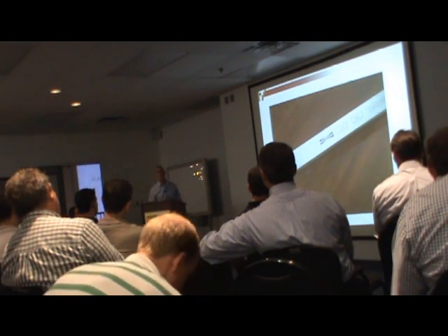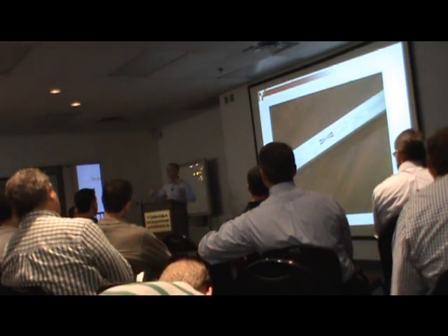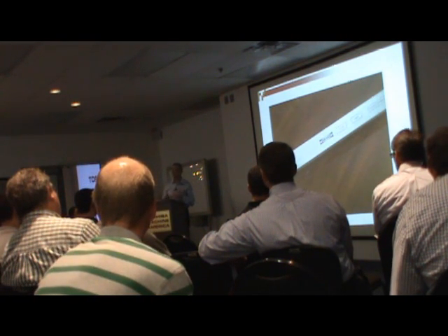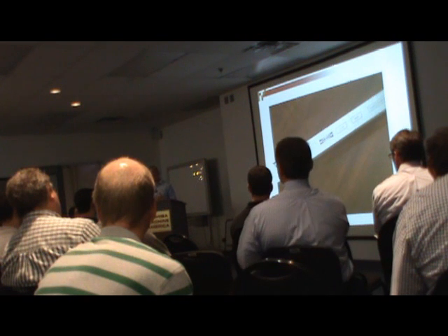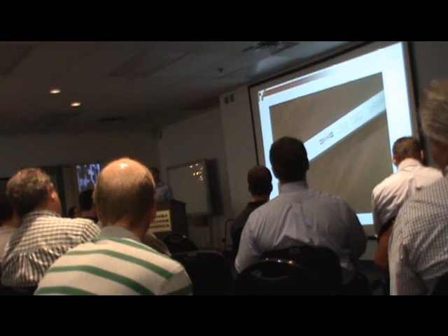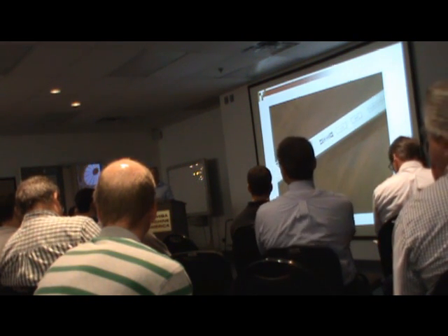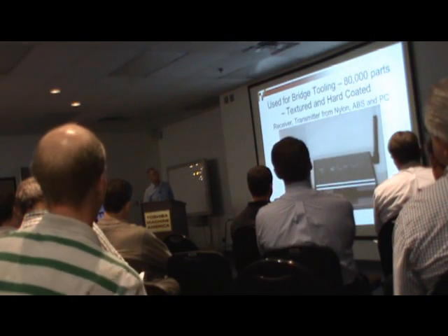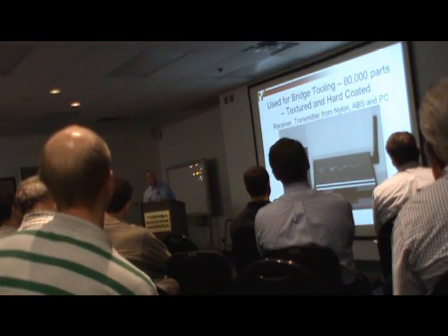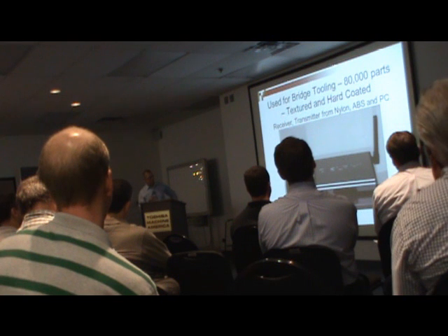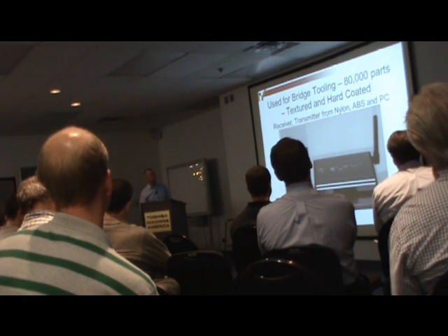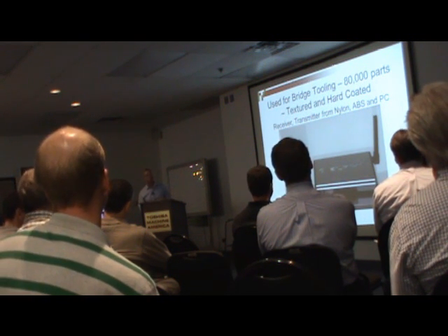When they did that, unfortunately, they had problems. They could not hold it with the same warp specs, so they had to change something. We ran some extra parts for them while they did their design changes, etc. Again, living proof that we don't experience the same issues in many cases in aluminum tools as you do with steel. Parts are back there. We've run over 80,000 parts. This is a production aluminum tool we did in 3 weeks. There's 12 different components.